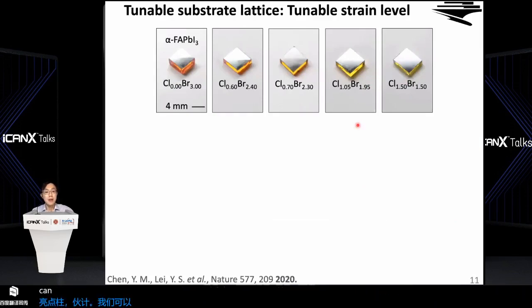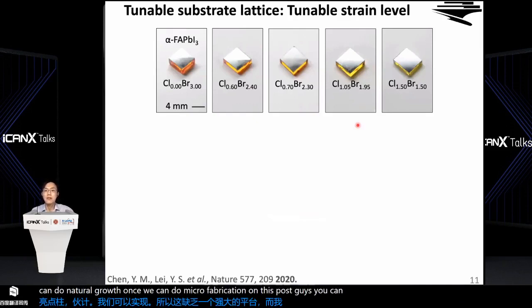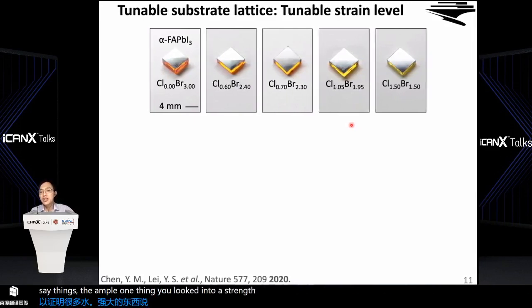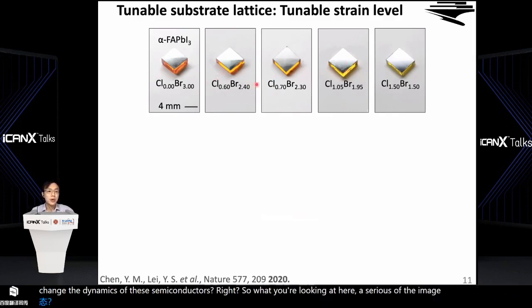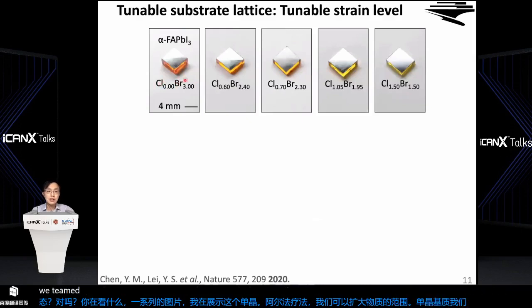Once we can do epitaxial growth, once we can do microfabrication on these perovskites, then we can demonstrate a lot of very powerful things. Say, for example, one thing we looked into is strain engineering. Why strain engineering? Strain has been used very widely in industry to tune the carrier dynamics of semiconductors, right? So what you're looking at here are a series of images showing single crystal thin films of alpha FAPI. We can grow them on a range of single crystal substrates whose composition we can tune. So you can see here, when we tune the composition of the perovskite substrates, the lattice structure changes, and there's also a band gap change.